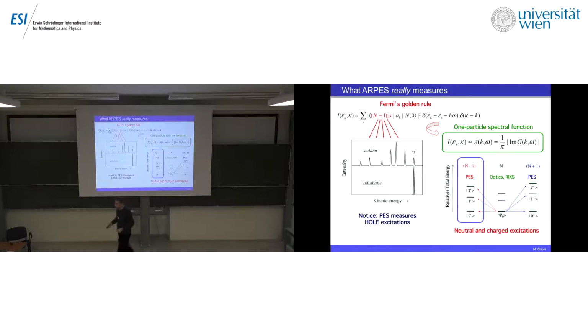In ARPES, what we measure is a transition between a ground state of a material and an excited state where we have removed one electron. Now, under some hypotheses, which are actually in general verified, what one observes then is the projection of this state, where I have removed one electron from the ground state, on all the possible excited states of the n-1 particle system. Now, you can work out this expression, do a little bit of algebra, and see that this is actually proportional to a very interesting quantity, which is the single particle hole spectral function. And this is something that you can calculate directly if you have the Hamiltonian.